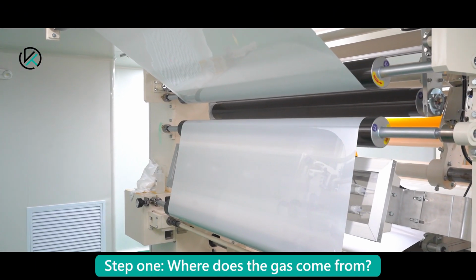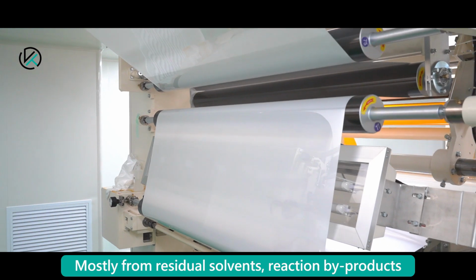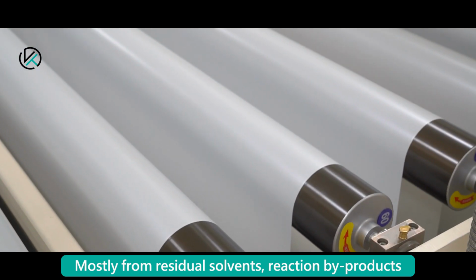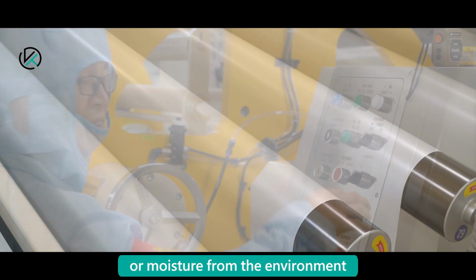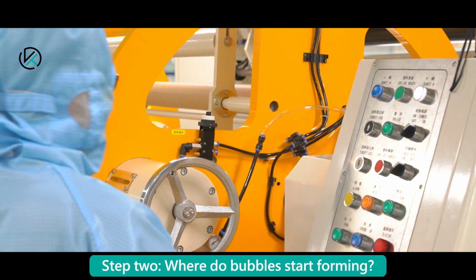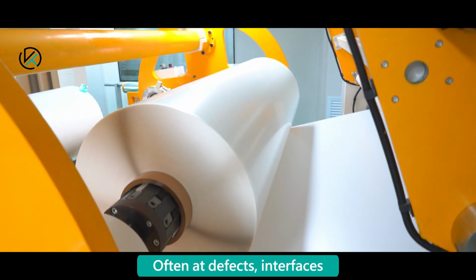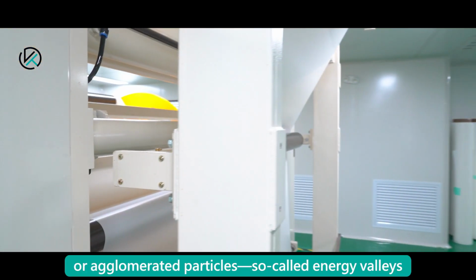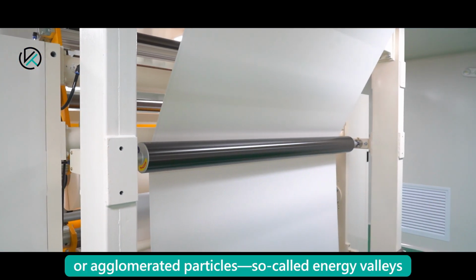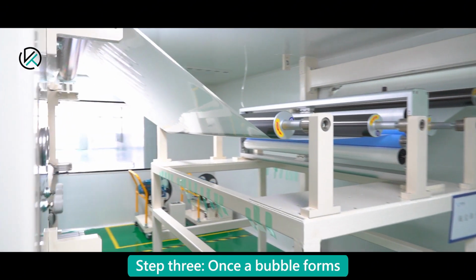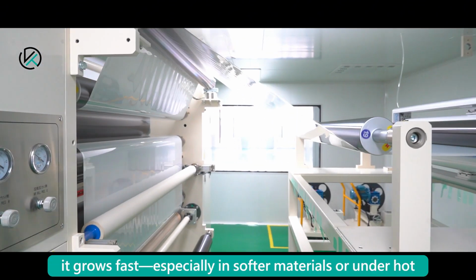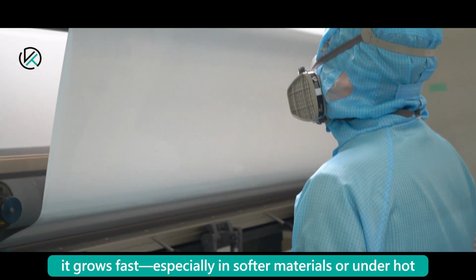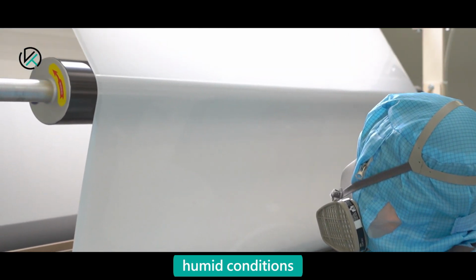Step 1. Where does the gas come from? Mostly from residual solvents, reaction byproducts, or moisture from the environment. Step 2. Where do bubbles start forming? Often at defects, interfaces, or agglomerated particles, so-called energy valleys. Step 3. Once a bubble forms, it grows fast, especially in softer materials or under hot, humid conditions.